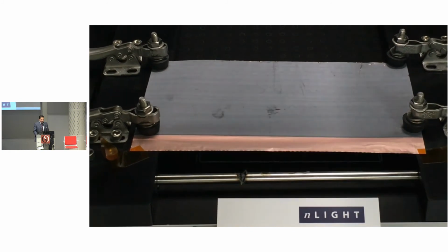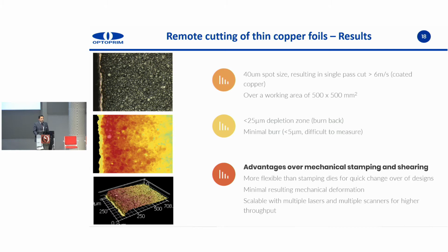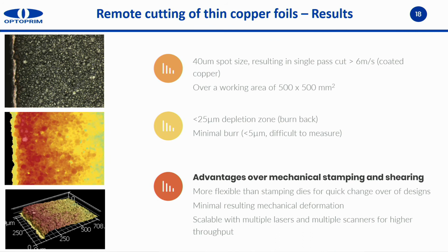And here is the result. As you can see, it is a very fast and very nice cut. Afterwards we had an overview of the result on the cut side, and we were able to achieve what the customer was asking for: a depletion zone below 25 microns, so the area where the overlay part is still present, and a minimal burr of the cut. The advantage of this approach is that it is more flexible than mechanical cutting, so you can change shapes, and it is a modular design where you can add multiple lasers and multiple heads, and so have a higher throughput.